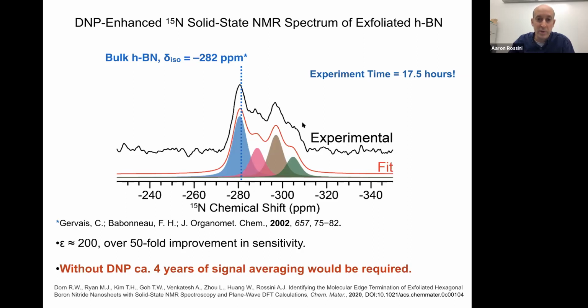So if we look at the spectrum, we can see 4 different isotropic chemical shifts. This peak at about negative 282 ppm is the known chemical shift of the nitrogen in the bulk of the hexagonal boron nitride.